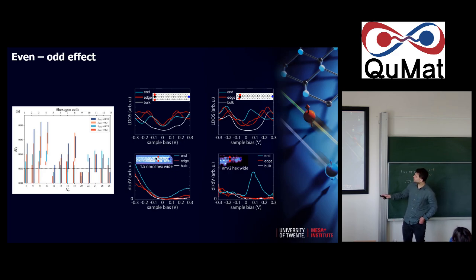And we think that we are approximately in this range over here. For 3 hexagons wide, you see that it's in this trivial range for the staggered mass that we have. And then eventually for 6 hexagons wide, it becomes topological. So everything between 3, 4, 5, for the staggered mass that we have, is trivial.